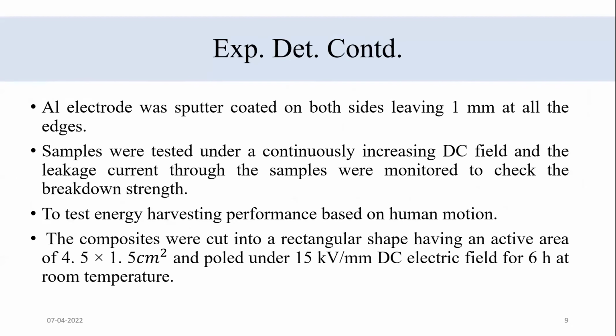Then the film prepared was sputter coated on both sides, leaving 1 mm from the edges. Then the sample was tested by continuously increasing the DC field, and the leakage current through the sample was monitored to check breakdown strength. The test of energy harvesting performance was done based on human motion.